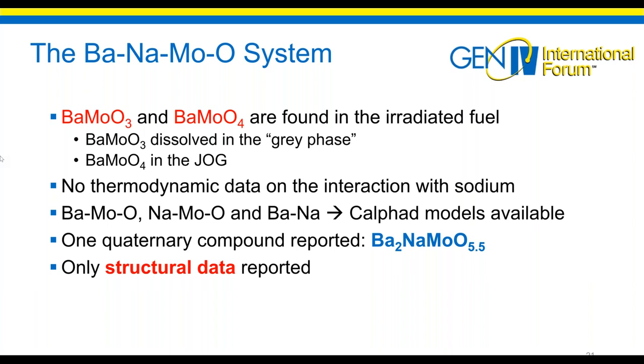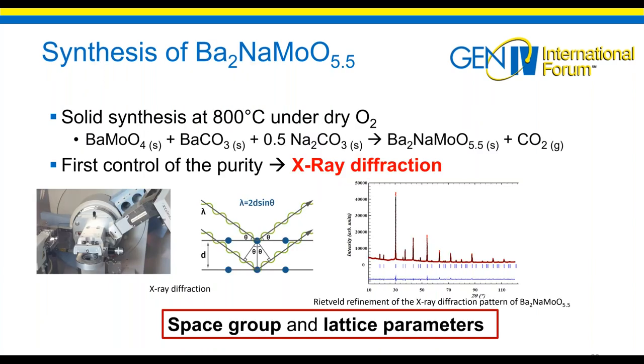So with some experiments on the quaternary phase diagram, we would be able to get the modeling of this phase diagram. One quaternary compound was reported in the literature, which is Ba2NaMoO5.5, but only structural data were reported. Therefore, we decided to synthesize this compound by solid state synthesis at 800 degrees C under dry oxygen, starting from barium molybdate, barium carbonate, and sodium carbonate, to get the pure compound and then to perform thermodynamic measurements.